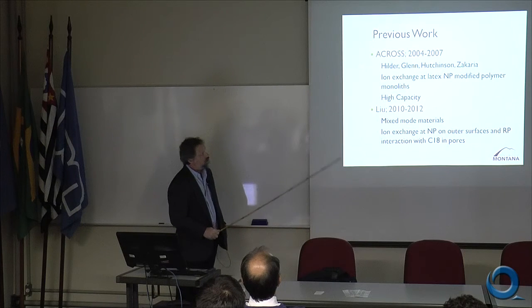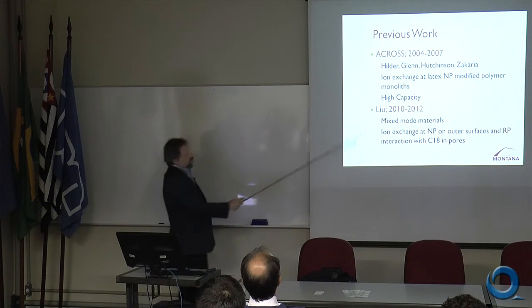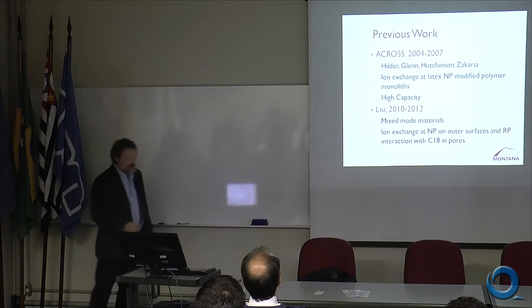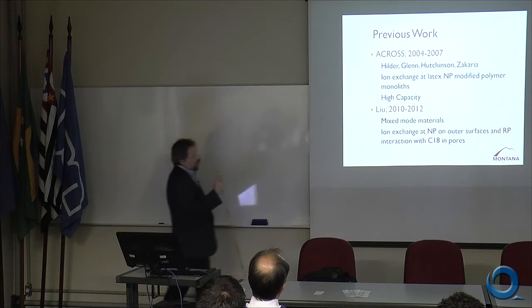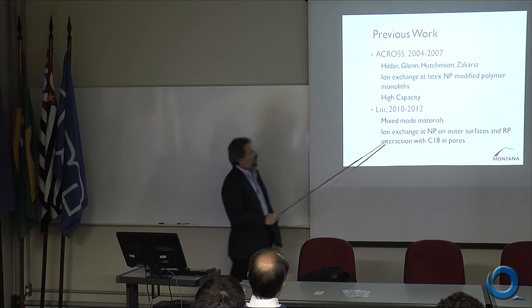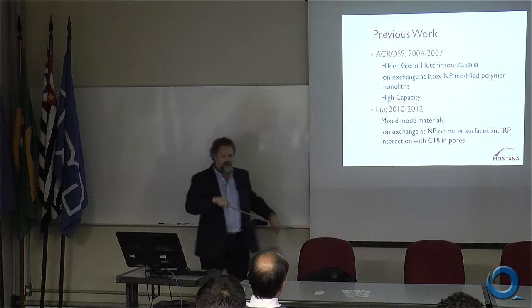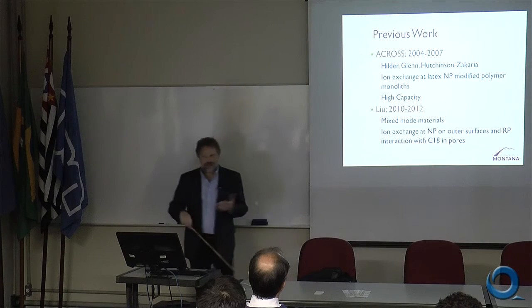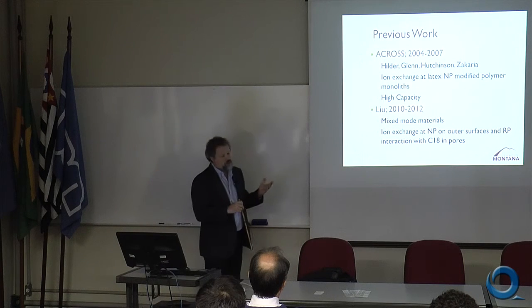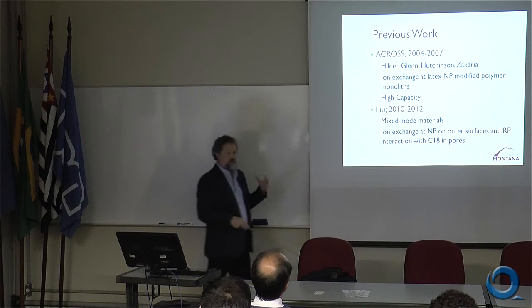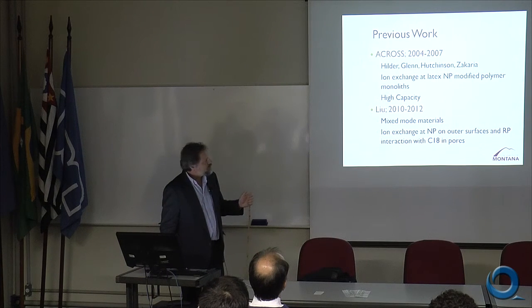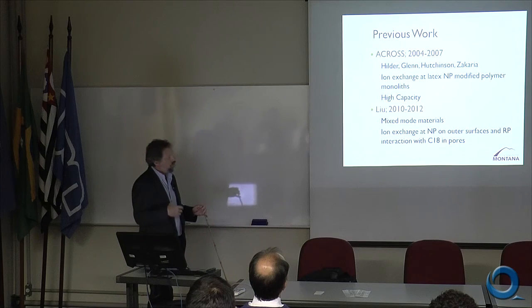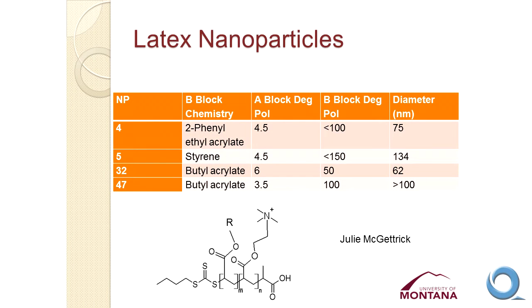ionic latex nanoparticles. And then more recently, some interesting work where this author took silica surfaces and adsorbed nanoparticles to the outer surfaces and had C18 octadecyl silane modification of the pores. And so he was able to develop mixed mode materials where he had ion exchange at the nanoparticles on the outer surfaces and reversed phase interactions with the C18 down in the pores. So there is some clear evidence that we could do some sort of ion exchange type separations in some cases.